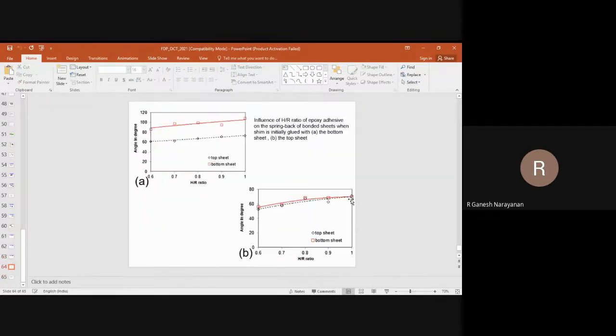So I will stop here with one last slide, that spring back can also be controlled using adhesive bonded sheets by varying its core properties. Like a tensile behavior can be controlled, forming behavior can be controlled. Similarly, spring back can also be controlled. This is one example. Hardener to resin ratio, if you change it, the best combination is 0.8. But if you decrease or increase it, you will see that with increase in hardener to resin ratio, angle in degrees is increasing, and the least one, 0.6, is the best.